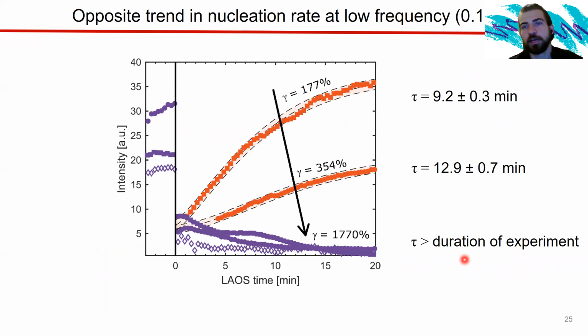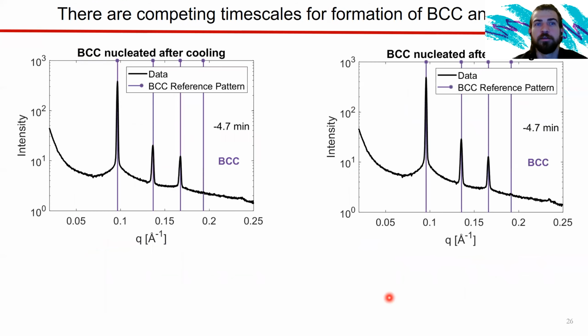So if we look at this lower frequency, 0.1 Hertz, you can see that as we increase the strain amplitude, we get the opposite effect. And actually our time scale is getting longer and longer until it's actually longer than the duration of the experiment. We only have a limited amount of time at the beam line.